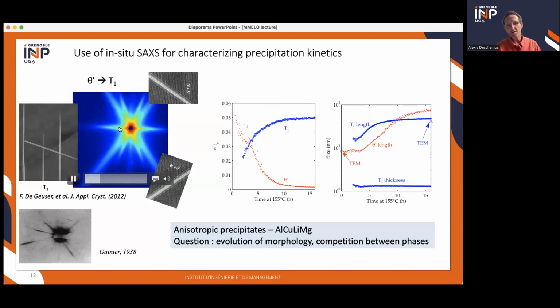And so you can see the evolution of the streaks. The streaks are really the same principle as if you do some light diffraction with a laser by a slit, a Young slit, then you get a streak. And analyzing these streaks, you can get all the parameters of the particles, the thickness of the particles, and their diameter. And you can show, for instance, that the T1s are a single unit cell thick throughout the heat treatment. So they are 1.2, 1.3 nanometers.